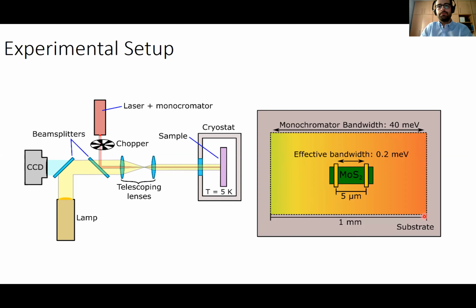We use this large beam in order to illuminate the whole sample, and this gives us a very high bandwidth of the beam. But for us, the important part of this beam is the optically active zone of the device, that is between the drain and source of the phototransistor, and the sample acts as a secondary slit that gives us an effective bandwidth of 0.2 millielectron volts, giving us a very high spectral resolution. Once we have the setup,